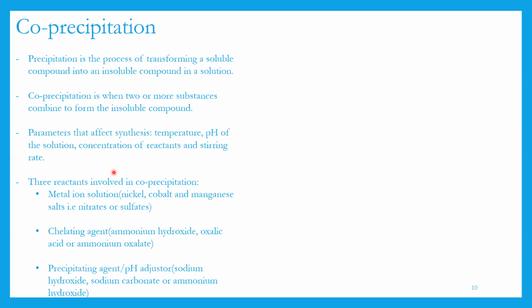Normally the salts we use are either nitrates or sulfates, as they easily dissolve in solution. And then you have the chelating agent. So you have these three metal ions, and they are all separate in solution. To combine them, we use a chelating agent, which can either be the ammonium ion in ammonium hydroxide or the oxalate ion in oxalic acid or ammonium oxalate. And they combine these three ions.